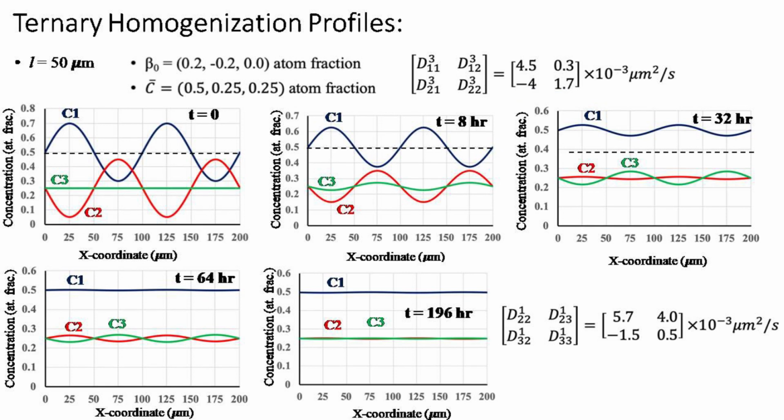So, we expect that the interaction of 1 on 2 will be great, but we can see, because the flux of J2 is given as minus D21 dou C1 by dou x minus D22 dou C2 by dou x, the gradient of 2 is also high to start with.